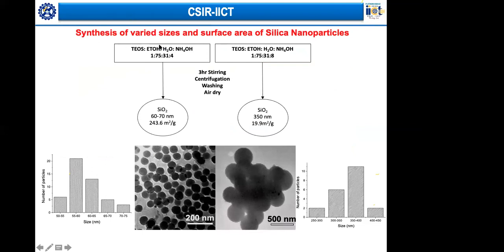As I said, by changing the reaction conditions a little, like 4 units of ammonium hydroxide and 8 units of ammonium hydroxide, you can see the size difference. These are all uniform, about 60 to 70 nanometers in size. This one is about 350 nanometers in size when you have taken 8 parts of ammonium hydroxide.